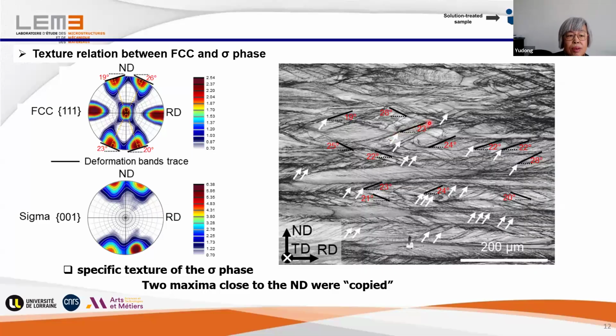And so we made a texture analysis, and we see for the stacking faults on the slip bands, this slip plane should be the 111 plane because it's an FCC crystal structure. Then we plot the FCC pole figures here, and be careful, it's not expressed in the rolling coordinate system. It's in this microstructure coordinate system. And we also searched a little bit and found that the 001 plane of the sigma phase has some correlation with the FCC plane. Interestingly, only these two pairs of 111 plane are coupled with this 001 plane, and not the other 111 plane here, you see?